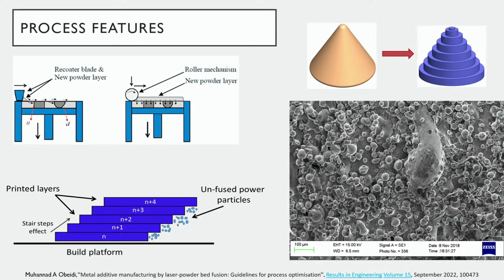So how did this happen? When the laser beam starts from here and then moves to there, with reference to the previous layer, because it's shorter, we have this roughness which is called stair steps. That's number one reason of the roughness. Number two, we have powder surrounding it everywhere. Powder here, there. When the laser beam comes here and stops at this point, based on the CAD file and the dimensions, this is molten material here. And this is still powder that I don't need. And there will be like micro welding between them. This process is called sintering. So I have to get rid of these particles, the sintered particles, and the stair steps.